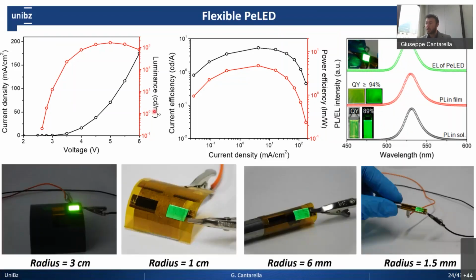The idea, as I was saying, is to realize flexible devices. So what you see here is our device under a specific voltage from a radius of 3 centimeter down to a radius of 1.5 millimeter. Clearly, the lower the bending radius is, the more these black spots, and therefore the failure mechanism, occur in our LED. So you can immediately see this one here down to a bending radius of 1.5 millimeter. Our LED starts experiencing some failures, so the presence of these black spots starts to increase.